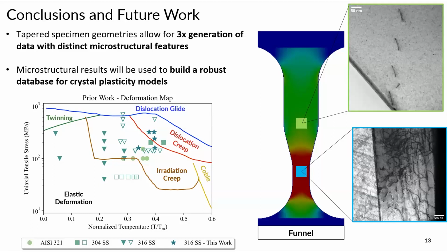It took a while. We're actually moving to DIC, or digital image correlation. So I'm running an experiment on Monday where I use sandpaper on half of the sample and then use high temperature carbon paint on the other side. That way we're not deforming the surface, because based on your grit, you then have a damage depth within your sample. Previously it didn't really matter because the damage depth ended up being larger than our sample thickness, so it was uniform damage introduced, but that's not a great way to run experiments. And so we're trying to do it where we're not damaging the sample. Does that clarify the question?